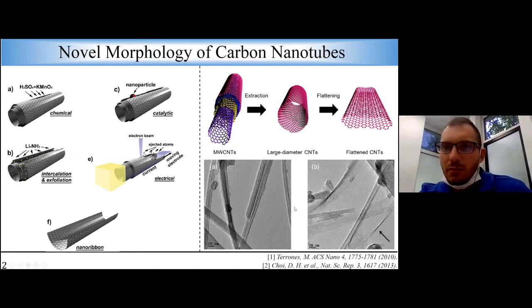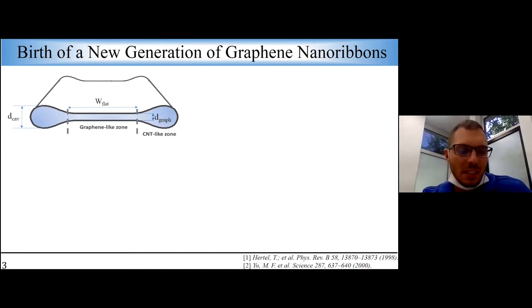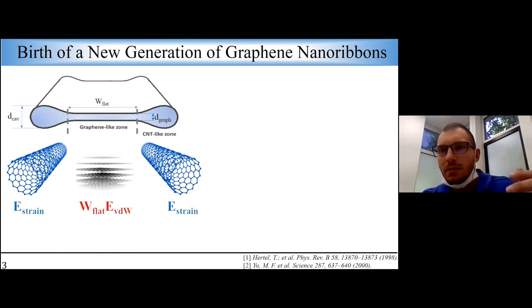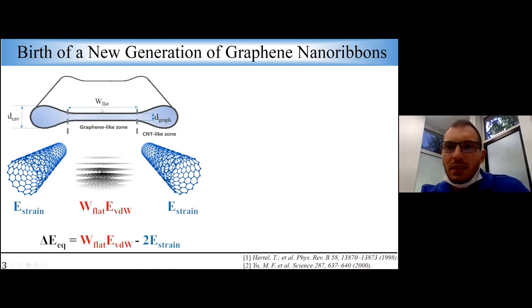However, given the complex architecture of this novel class of flattening deformation, it might be useful to consider the following schematic representation, where we have two edge bulbs whose geometry resembles the canonical configuration of cylindrical single-walled carbon nanotubes, which are connected by a central flattened region, which is very similar to simple bilayer graphene. So for this hybrid system between circular carbon nanotubes and bilayer graphene, the energy balance is given by a competitive process between the van der Waals forces exerted in the middle against the repulsive strain energy due to the deformation